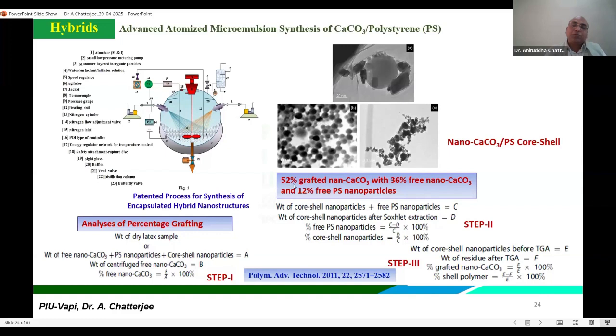Here you can see 52% grafted calcium carbonate for A, with 36% free nano calcium carbonate and 12% free polystyrene nanoparticles. In the microemulsion process, grafting of the polymeric shell on solid particles is very important. Depending on the addition of monomer or conversion of monomer to polymer, that is very important in terms of grafting of the polymeric shell on the surface of solid nanoparticles.